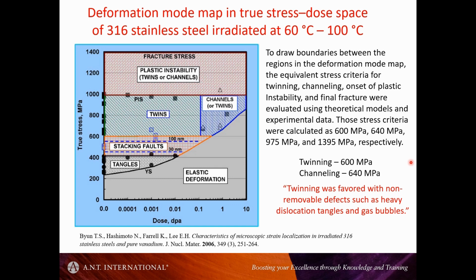And the last slide for this session is here, and it's just a copy of a figure from work by Thak Byun, who did some excellent work on strain localization and mechanical properties of irradiated steels, and he's mapped out what types of deformation one gets as a function of the stress and as a function of the dose in 316 stainless steel. This is a low temperature irradiation.